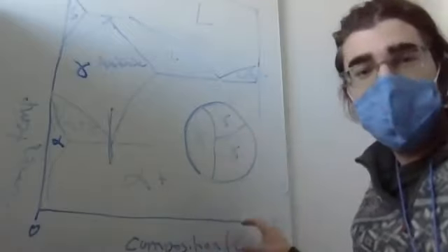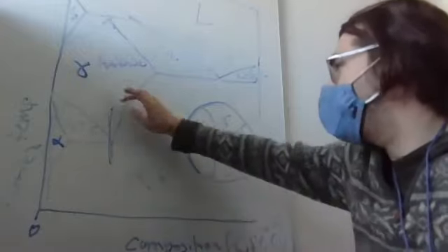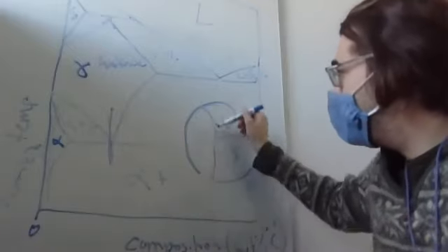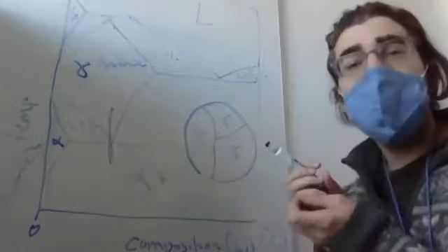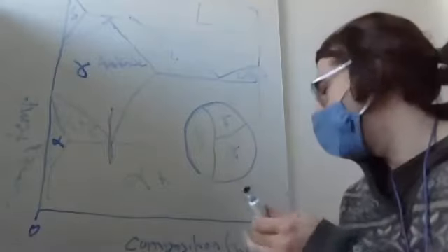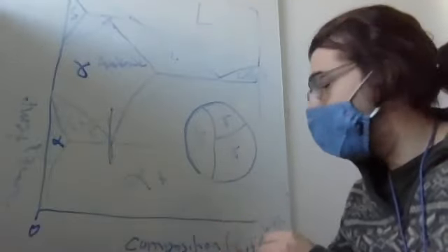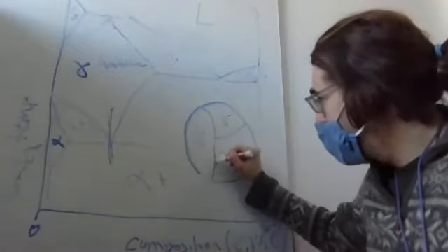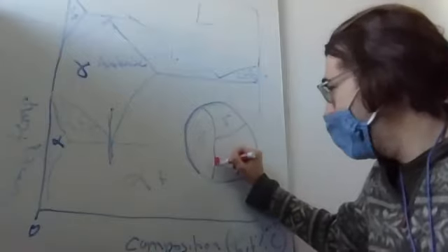And this is a cross section of grains of austenite, right? They exist. And as we cross this eutectic point, what's going to happen is at the grain boundary here, we're going to have a localized region of a carbon-rich phase. Because of random chance, there's going to be a little region where there's a little bit more carbon, and that will form cementite, right?